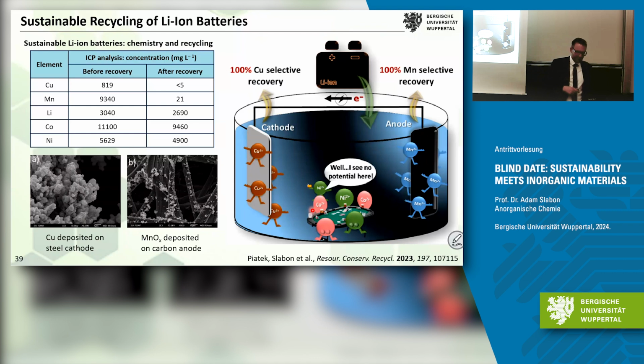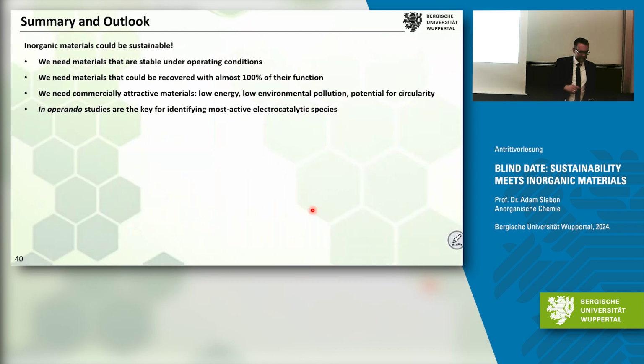So coming to the main question: can materials be sustainable? Inorganic materials - they could be sustainable, I would say, but stability under operating conditions is an issue, for example in CO2 reduction. You need a longer process of time where you can analyze the catalyst, because if you have some ppm amounts of iron in the solution, they will get adsorbed on the surface and you end up with a catalyst for water reduction instead. So stability is a problem.